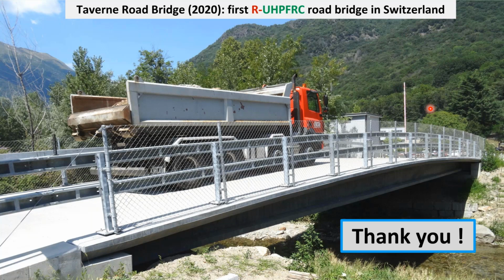And what's the time between laying the UHPFRC and opening the bridge to traffic? In case we put the layer of asphalt on top of it, we have to wait 1 week after casting in order to put the asphalt layer on the UHPFRC. So roughly 8 days. And were there differences in cure time between the deck and the abutment diaphragm when they were cast monolithically? Well, I suspect that the volumes, the masses are different, so there could be a difference, but we did not notice any. Of course, if we had measured temperature evolution over time, then we would have measured the difference. But overall, it is not relevant.